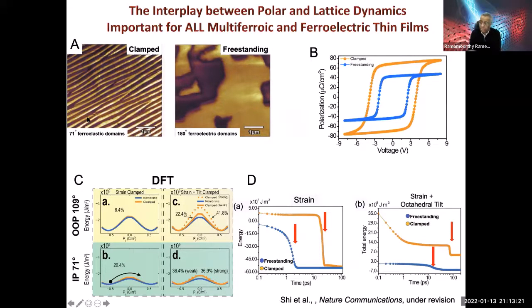If I simply lift off that BFO, exactly the same sample, the domain structure dramatically changes. You don't have the stripes. There is no ferroelastic component. Instead, you see very nice 180-degree domains. If you measure the ferroelectric hysteresis, the coercive field comes down dramatically by about 35 to 40%. The blue is the freestanding, and the yellow or the orange is the clamped film.